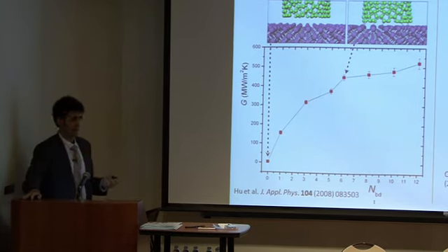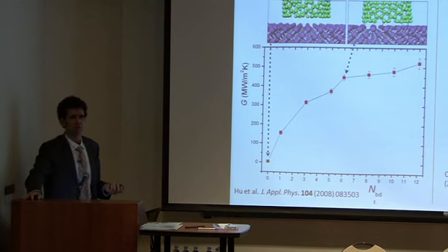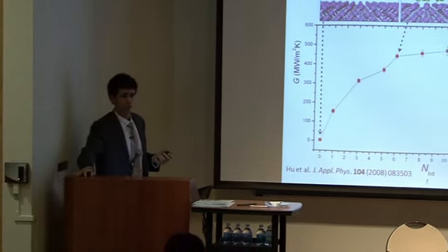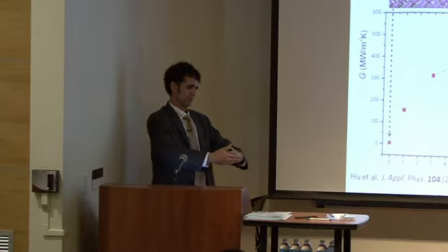One is that carbon nanotubes are essentially chemically inert. They're not very reactive. There's always a gap. We call it a van der Waals gap between the carbon nanotube and whatever else you try and put it in contact with. And that gap, as you would imagine, acts like a huge barrier for these waves that are propagating through these materials. It inhibits their heat flow.